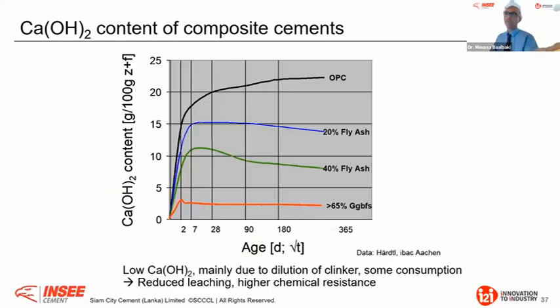And when we come, for example, to leachability, when I look at calcium hydroxide from OPC for different percentages of fly ash or slag, you see the amount of calcium hydroxide drops drastically. We will always have enough to keep a certain basicity pH in your concrete to protect your reinforcement, definitely. There is no worry about this. But what is more important, the dissolution, or I would say the leachability, will have high chemical resistance, just because we are eliminating a soluble salt, a kind of soluble salt, that is portlandite.